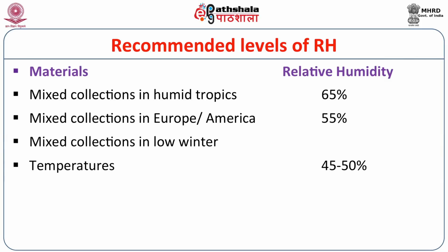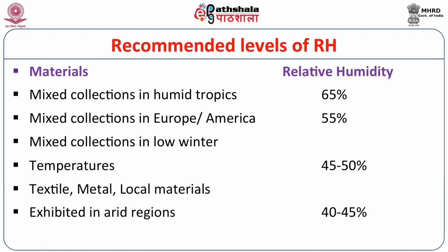A mixed collection in low winter temperatures should be 45 to 50%. And materials like textiles, metals, and local materials exhibited in the arid region should be 40 to 45%.